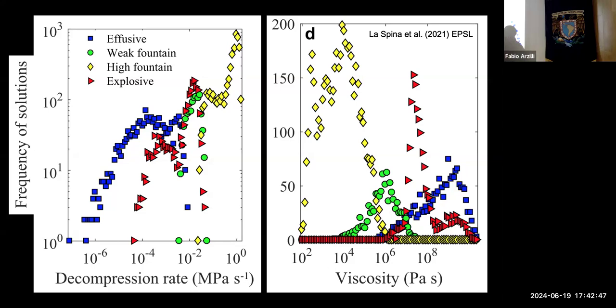So it means Plinian eruption. If we have a very fast ascent rate, we can promote high fountaining activity. And this is correlated with the viscosity. So high ascent rates, meaning fast decompression rates, means that crystallization kinetics has no time to form crystals because of disequilibrium, because the approach to equilibrium maybe is too slow. And so therefore the viscosity remains low because your magma will be liquid. And so therefore fountaining will be promoted, compared to highly explosive eruption where you have the right ascent rates and fast crystallization kinetics.